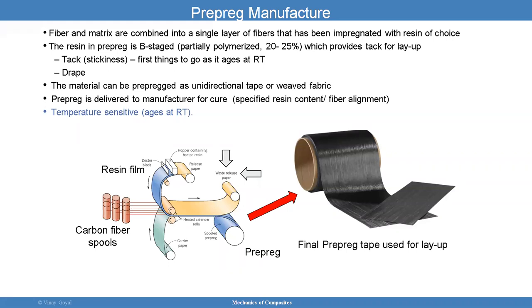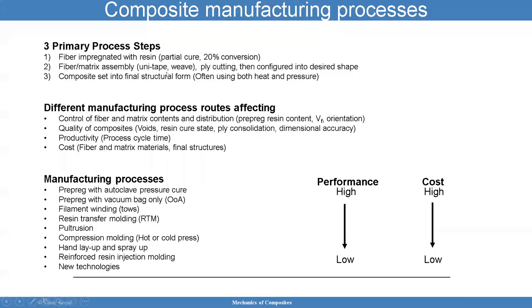The material can then be pre-pregged, and you can pre-preg as a unidirectional tape or a woven fabric. And then the pre-preg is delivered to the manufacturer for cure, and it's going to have a specified resin content and fiber alignment. They can be temperature sensitive. So sometimes these pre-pregs are shipped at frozen, cold temperatures to maintain the overall health of the resin primarily, okay?